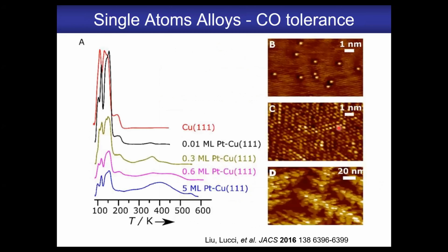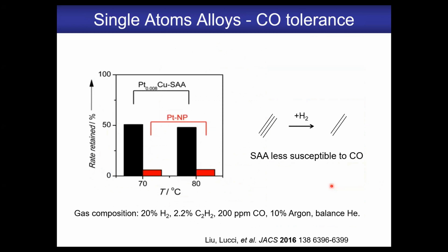Another thing we noticed during these experiments is we noticed the carbon monoxide, a common poison, binds more weakly to single atoms of platinum than to extended platinum, as you see here. So we went back to Maria's group and they tested this for the selective hydrogenation of acetylene to ethene in a flow reactor. And what they did is they compared to regular platinum nanoparticle catalysts. And when you add 200 ppm of CO, you see you lose 90% of the reactivity of the regular platinum nanoparticle catalyst, whereas you only lose half the activity of the 1% platinum catalyst because of that weaker binding of CO, that the reaction can proceed because more of the sites are not poisoned by CO as compared to platinum, which binds CO much more strongly.